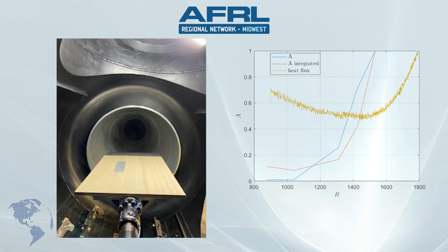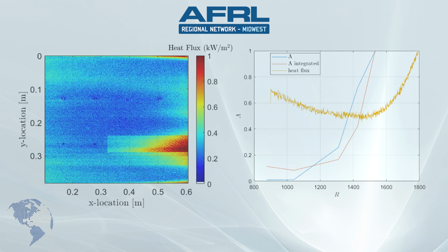But what's interesting about this particular test article is it also allows us to identify boundary layer transition via another common metric, which is infrared thermography, specifically surface heat flux. That yellow line along the same axial location along the model indicates an abrupt increase in heat flux much farther downstream than the PCB surface pressure sensors, which opens up a totally new, interesting avenue for exploring the underlying physics of this particular mechanism of boundary layer transition that we and our Air Force colleagues are extremely excited to explore in more detail.